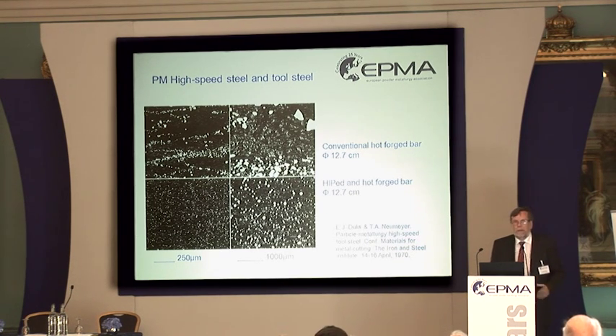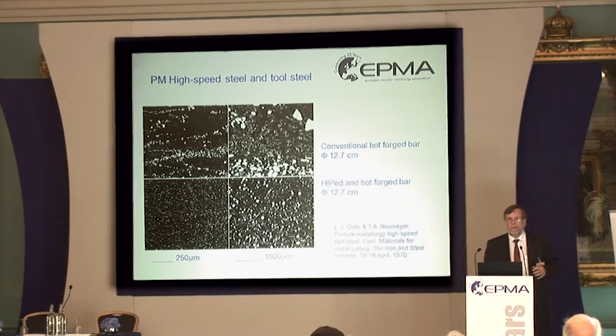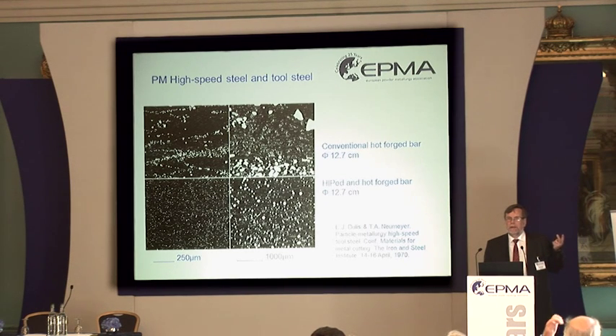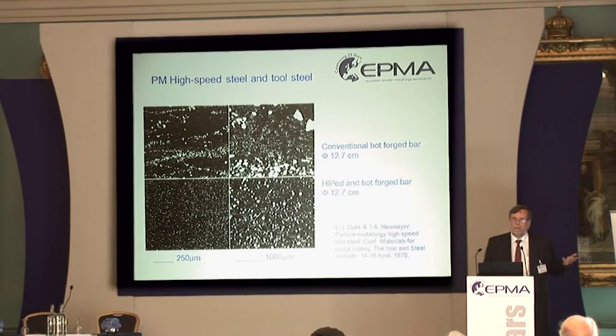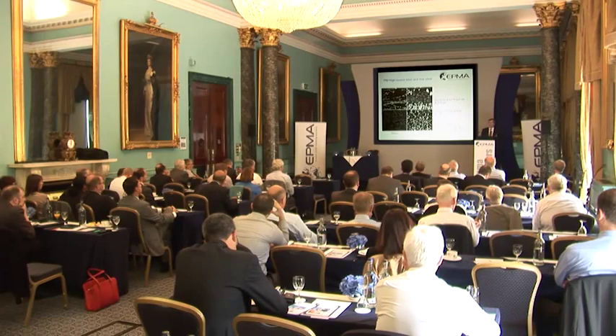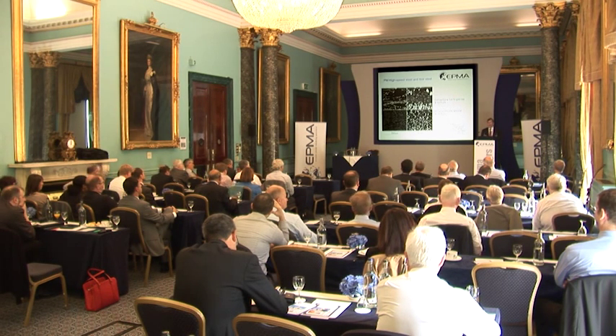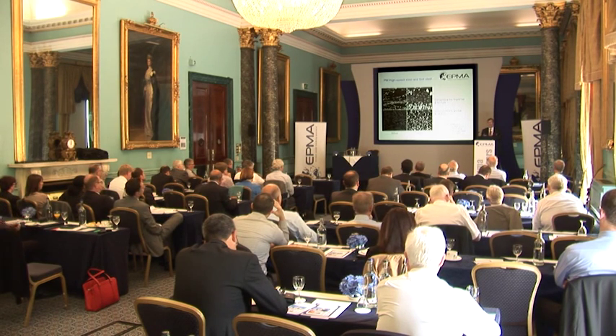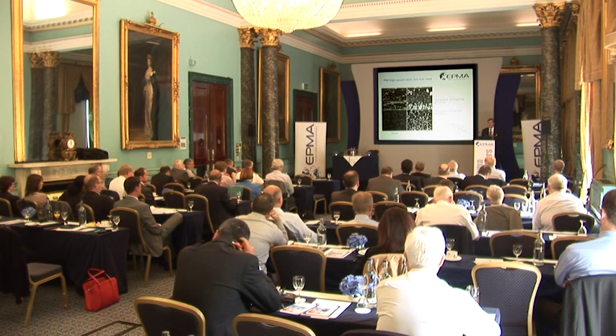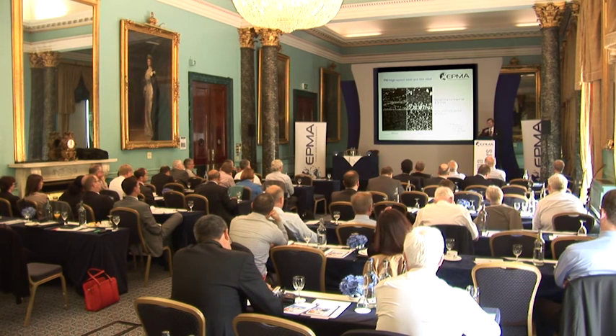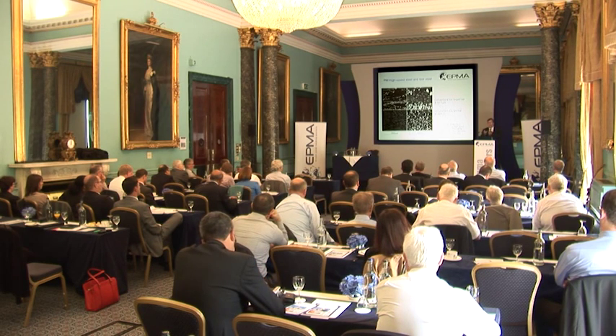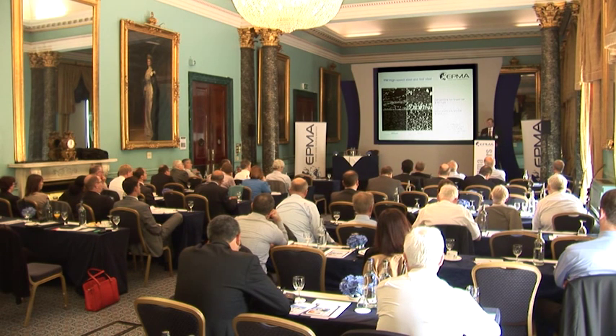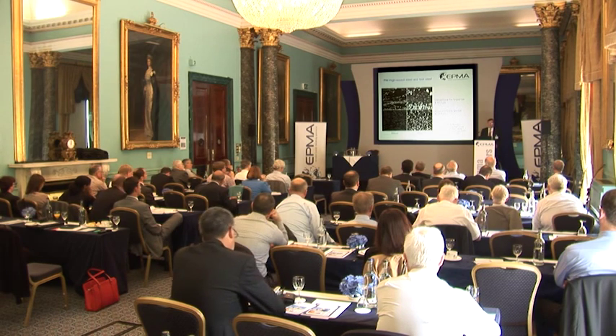And you can see the conventional bar forge has this carbide segregation and carbide layers. So by going from powder to the powder metallurgy route, you gain two things. One was improved performance, for example, in cutting tools. Lifetime could increase 5 to 7 times. But the limiting material property of high-speed steel in tool steels is hot workability. And hot workability is often addressed as reduction of area. With high-speed steels, you often have a reduction of area at high temperature of 20%. That is the limit of the hot workability, while on PM steel, you can have 80 to 90%. Very ductile.